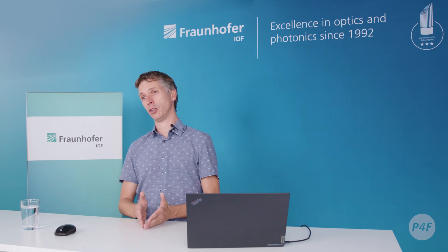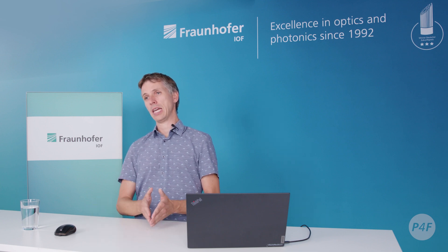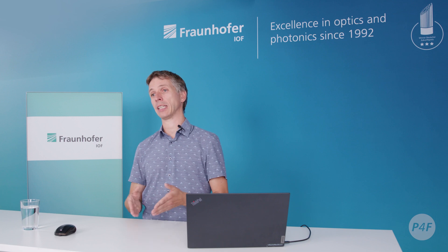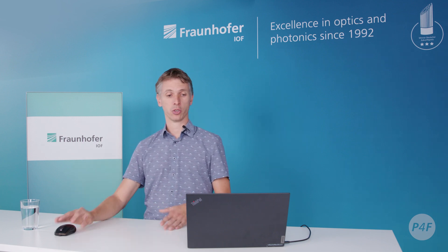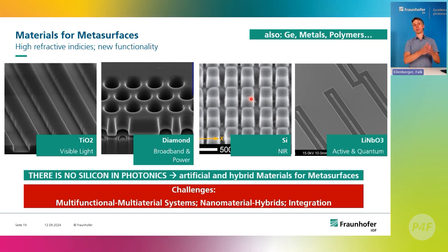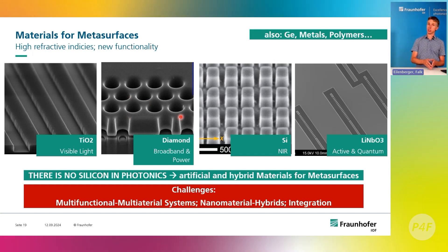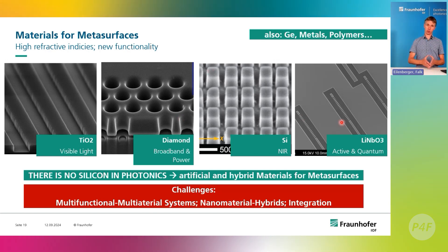It's not just about the structures; it's also about the materials and your ability to etch into them with very high quality. This is worth its own talk, but briefly: it's not just glass or silicon for the near infrared. It's also about high-refractive-index visible materials like titanium dioxide, extremely broadband materials like diamond, and electro-optically active materials that you can tune, switch, and modulate, such as lithium niobate. The challenge is combining nanostructuring technologies with these multi-material platforms to achieve the functionality you need.